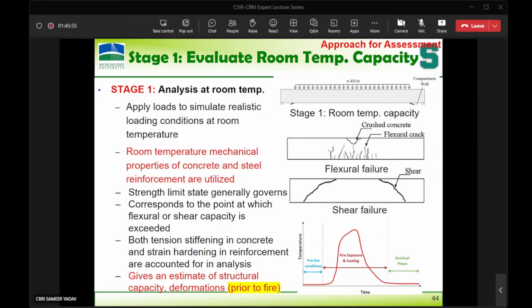You have to use finite element analysis to get the deformations, not just the stress. You need to know the residual deformations and the service load just before the fire, because after 50 years, whatever strength was used in the design stage is useless. You can take a core, you can do that. Also rebar: any reserve capacity is in the rebar. Tension stiffening and strain hardening can all be imposed into the analysis.